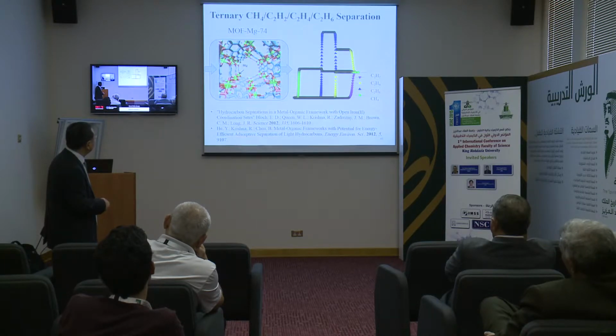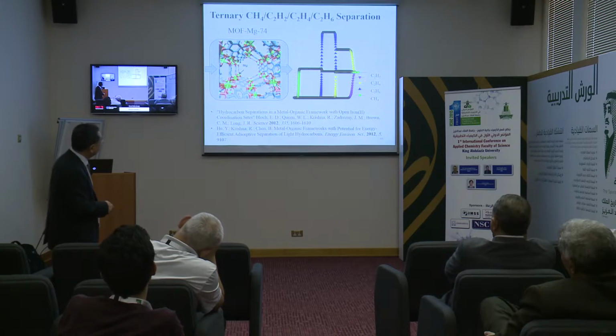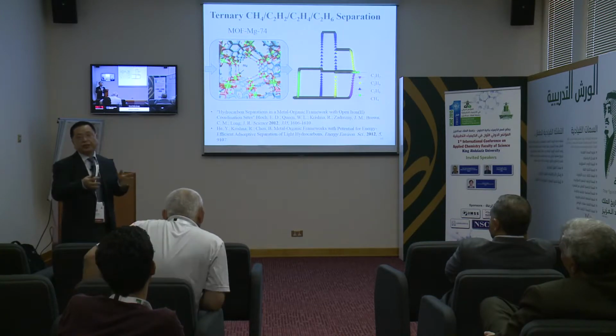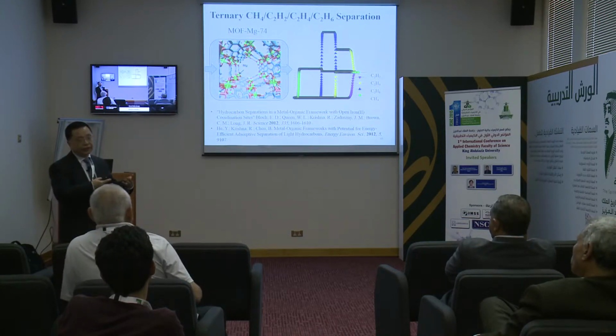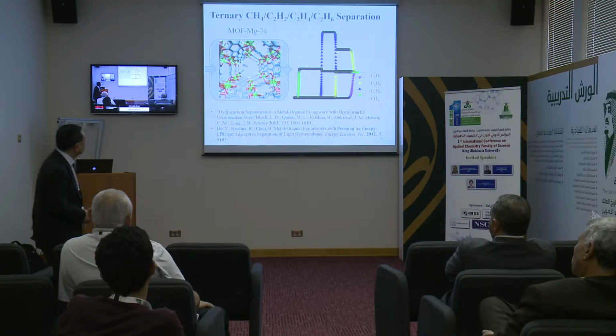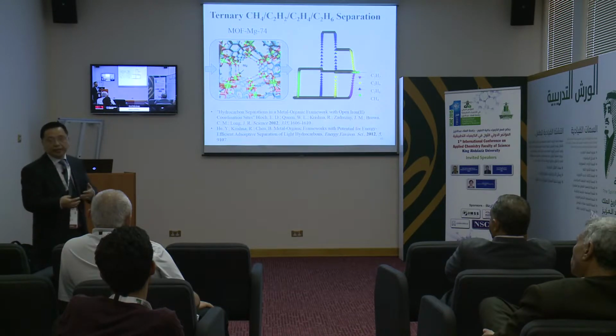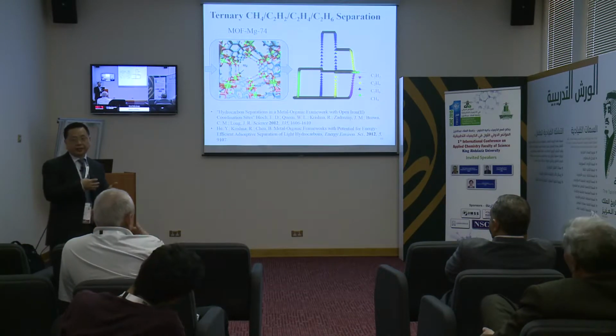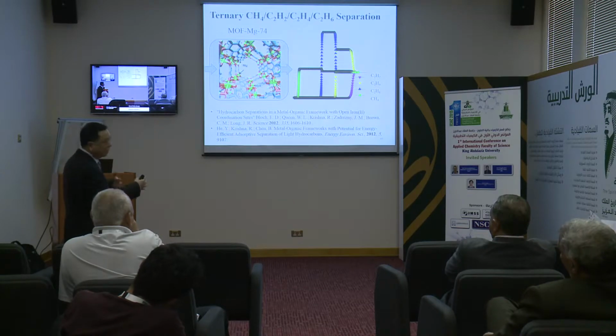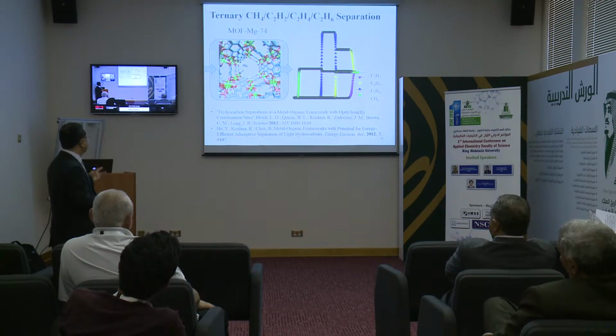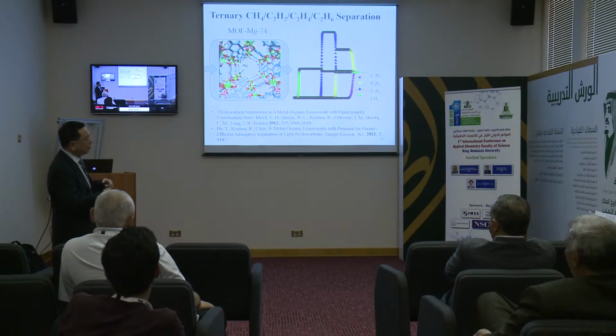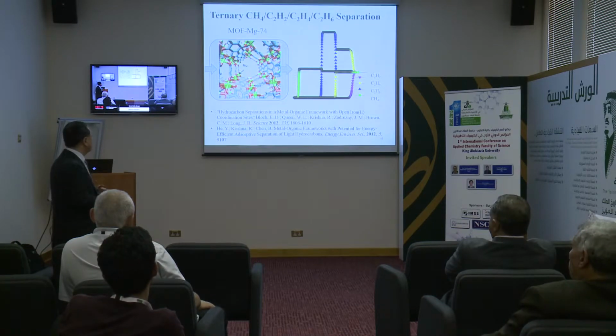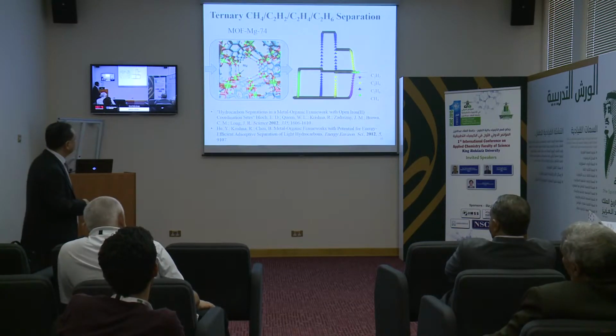And this one, the uptake is high for acetylene, because they have a high density of open metal sites, as mentioned, for acetylene storage capacity. But here there's a problem, because the open metal site also binds both acetylene and ethylene. So the selectivity is not so high. So that's the opposite one. The first one has good selectivity but the uptake is not good. But this one, the uptake is quite high, but the selectivity is not.